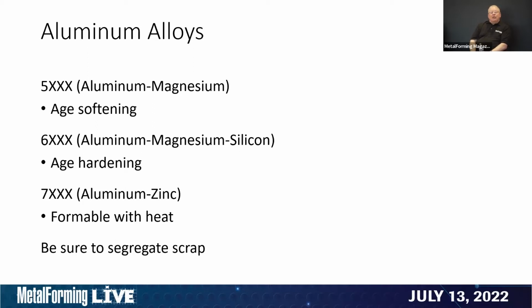With aluminum, the alloying elements that make the 5000 unique from the 6000 series, unique from the 7000 series, the alloying elements that give each of these alloys their unique properties, you can't intermingle them. If you do intermingle them, then you're going to wind up with a paperweight, and you will significantly degrade the value of your scrap. As a matter of fact, Ford, when they first introduced the F-150 in the 2015 model year, they installed a $60 million scrap segregation unit where they were able to keep the scrap stream from each part unique and return it back to their specific mill source. And that is possibly the most significant factor that allowed Ford to use aluminum alloys in a profitable manner. Wouldn't have been able to do so otherwise.